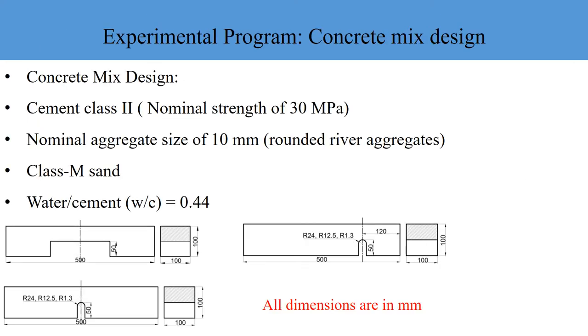To check the accuracy of the new TCD extension, normal concrete specimens were prepared in the lab. Schematic drawings show the dimensions of the plain specimens and the symmetric notched specimens. A set of specimens were also cast with an eccentric notch location. All specimens have a net nominal depth equal to 50 mm. Three different notch sharpnesses were considered: blunt notches with a root radius of 24 mm, intermediate notches with a root radius of 12.5 mm, and sharp notches with a root radius of 1.3 mm.